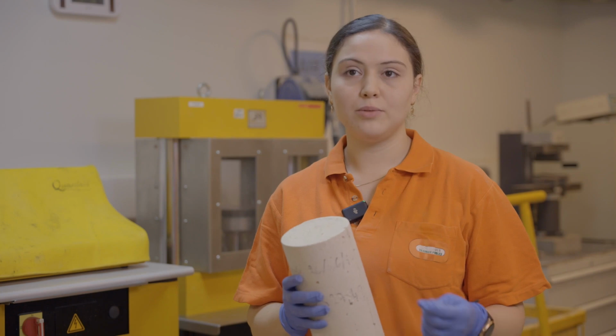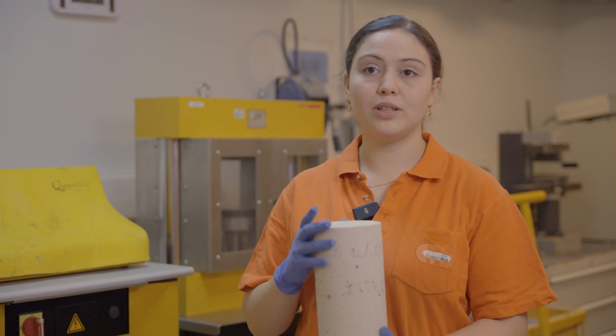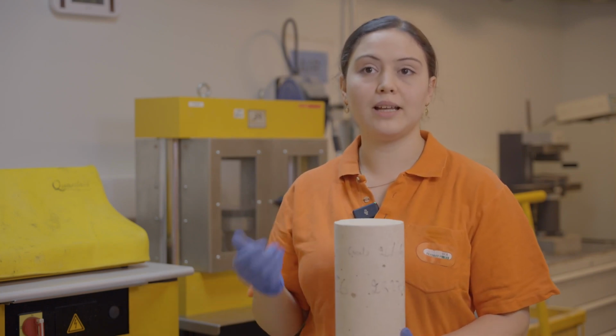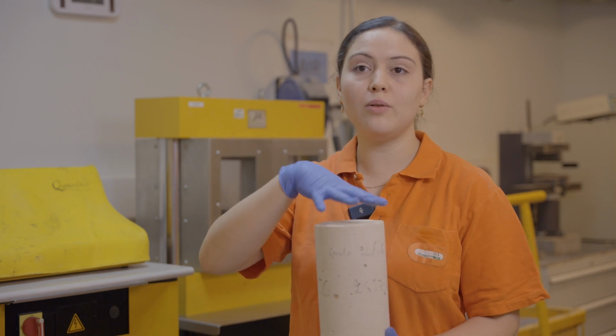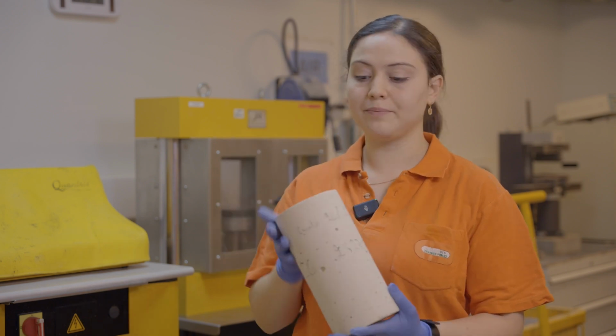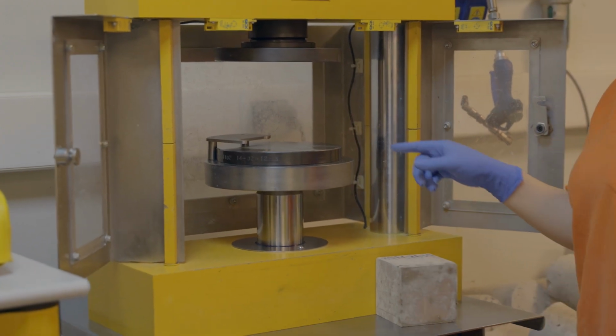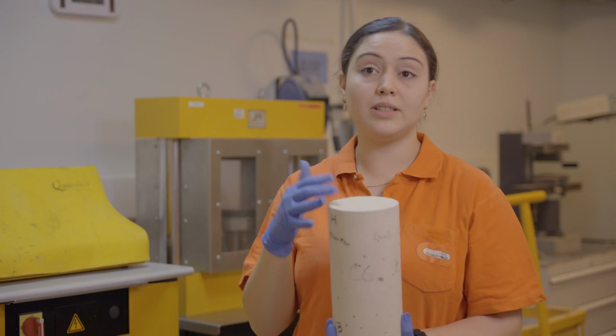After demolding and before performing the test, we make sure that the surfaces are smooth. Why? This is to ensure an even load on both surfaces during the test. The bottom surface tends to be smooth because of the mold, but the surface exposed to air often has irregularities.